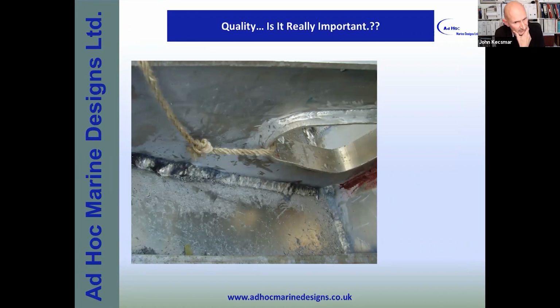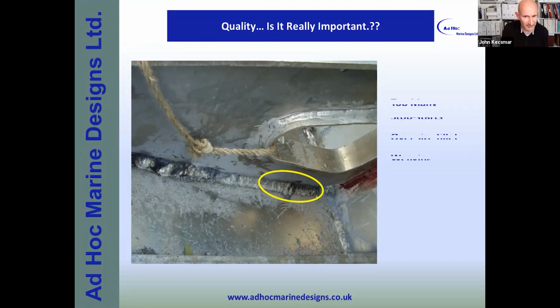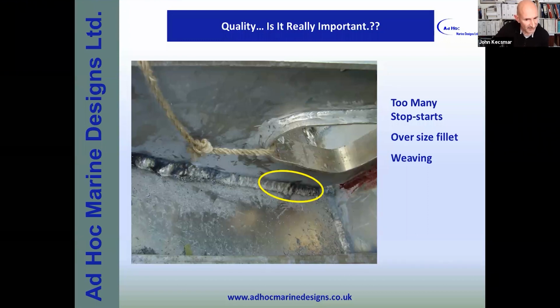So quality, is it really important? We can see here in this region, it's a beauty. There are just too many stop-starts, and we know stop-starts are notorious for cracking for several reasons. If the welders put too much heat in at the start or the stop, then you get a crater crack, and it doesn't take too long for that to start to initiate as a real crack. Also, if the welders are a bit too lazy to grind over the stop, there's going to be some natural crack behind it because there's going to be some lack of fusion. And there is an oversized fillet, which indicates weaving because of just poor lineup.